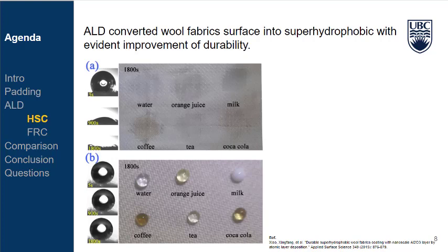Interestingly, the durability was evidently enhanced as shown in Figure A. After exposure to atmosphere for 1800 seconds, the static water contact angle of control wool fabrics decreased to almost 0 degrees, and that of ALD coated wool fabrics remained at about 160 degrees as seen in Figure B.